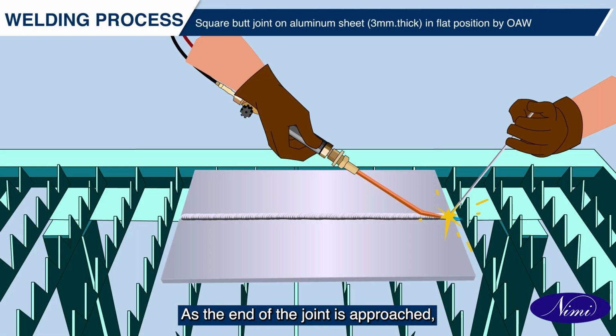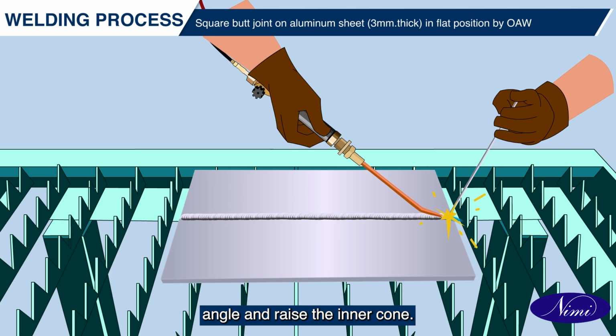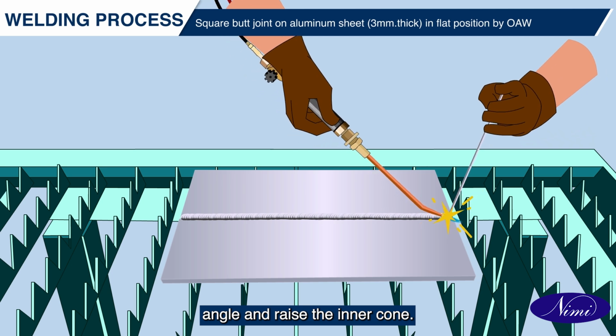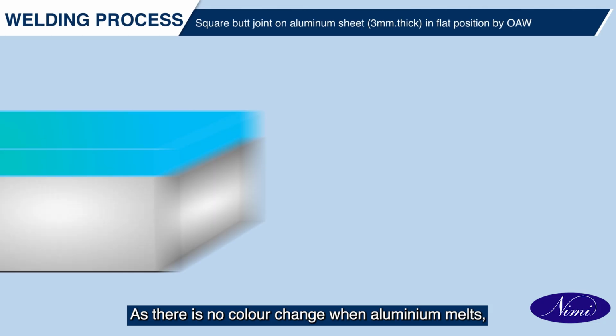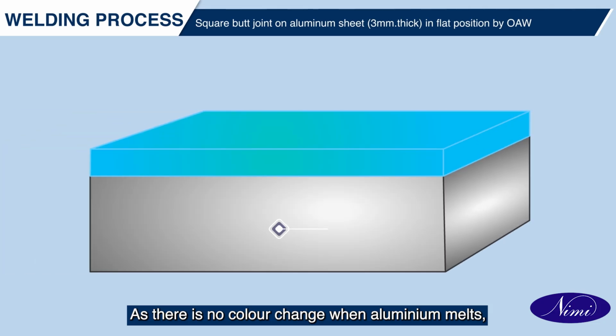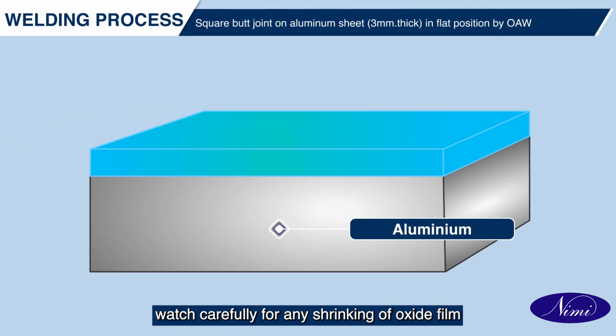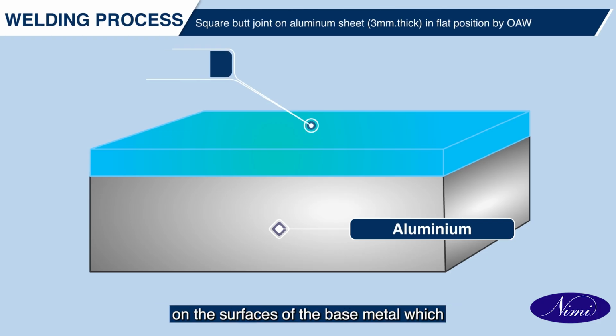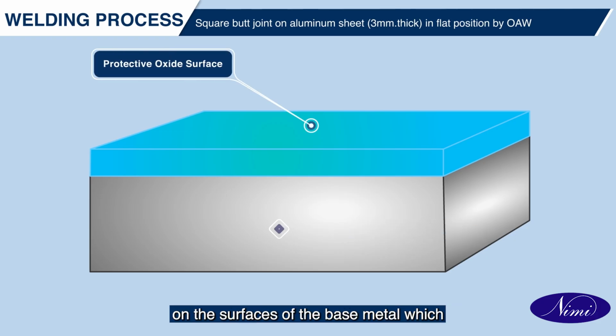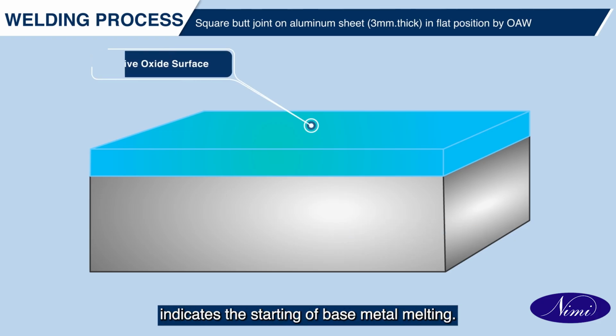As the end of the joint is approached, reduce the blowpipe and filler rod angle and raise the inner cone. This is done to avoid burn-through of the joint. As there is no color change when aluminum melts, watch carefully for any shrinking of oxide film on the surfaces of the base metal, which indicates the starting of base metal melting.